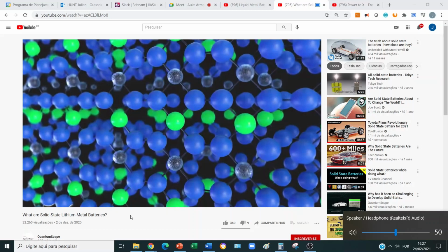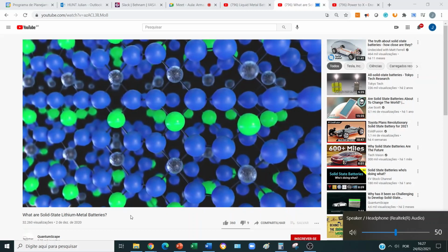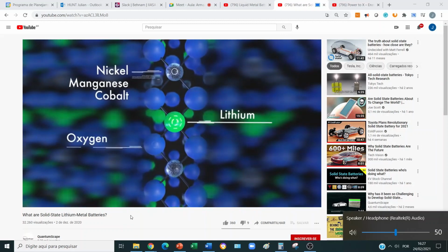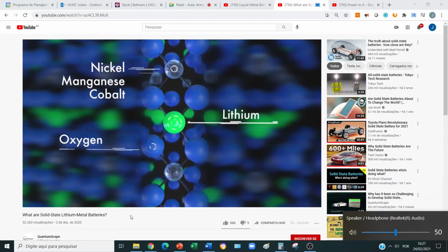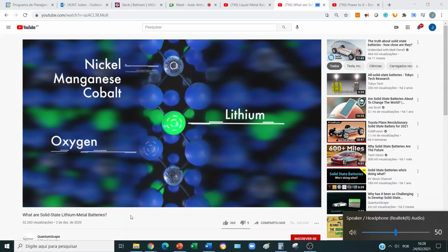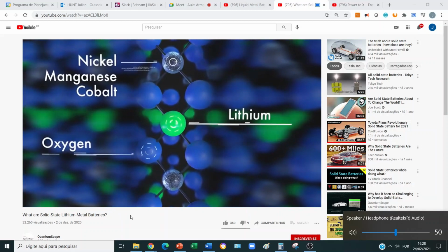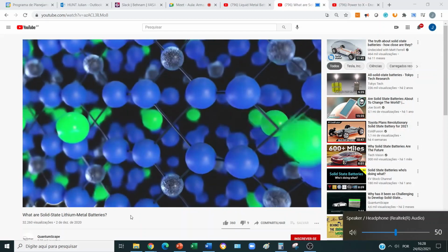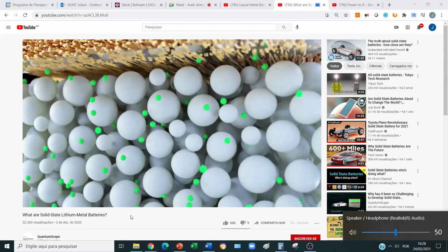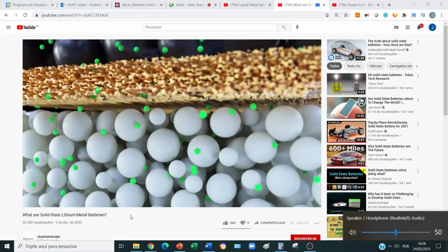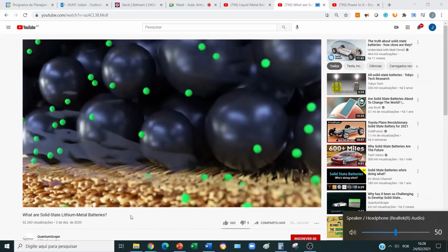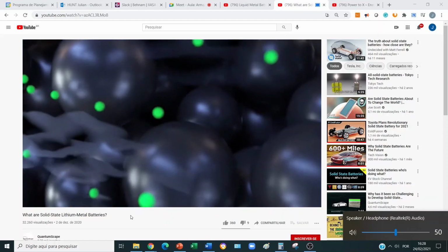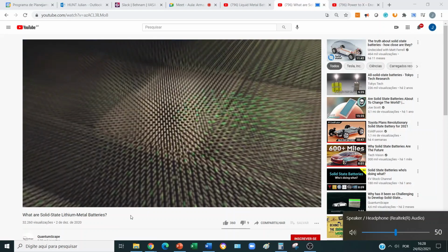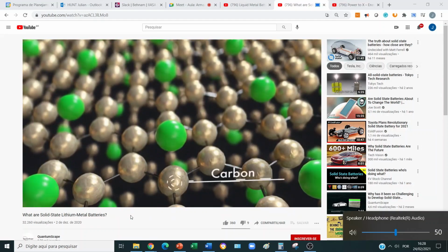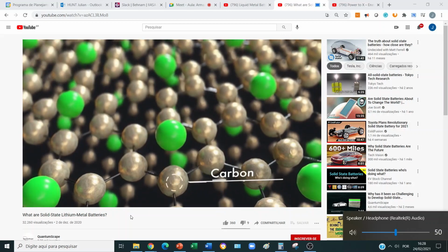Let's zoom in to look at what happens inside the cathode electrode particles. Each cathode particle is made up of a lithium-containing metal oxide, such as lithium nickel manganese cobalt oxide, commonly known as NMC. These elements form a stable structure to hold the lithium ions when the battery is in the discharged state. As the battery charges, the lithium leaves the cathode particle and makes its way through the liquid electrolyte, passing through the pores in the separator on its way to the anode. There, the lithium enters the anode particle, commonly made of sheets of carbon, sometimes adding silicon. The sheets of carbon host the lithium until the energy is needed, with 6 carbon atoms holding a single lithium ion.